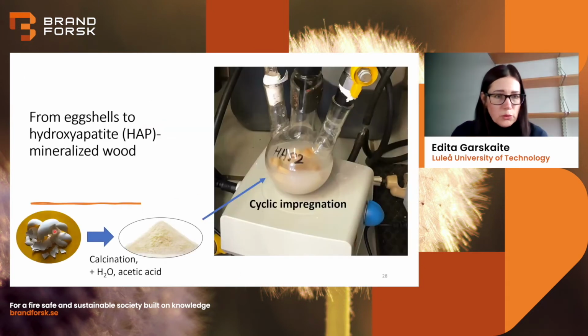So just briefly to remind, we take eggshells, calcine them, add water and acetic acid, and after drying we obtain powders of calcium acetate, which we use as a first solution. Then here we see these saturated wood blocks, small samples. This is actually after the second impregnation, because we see a little bit turbid solution.